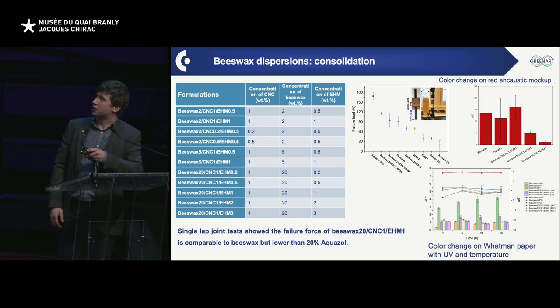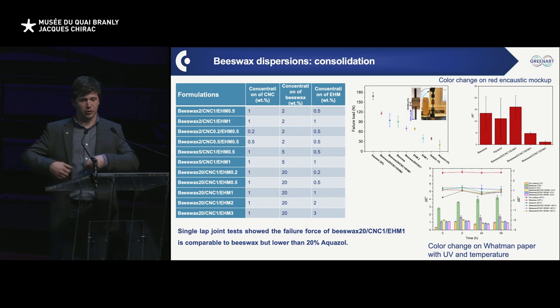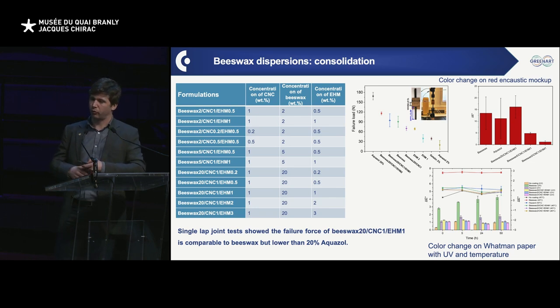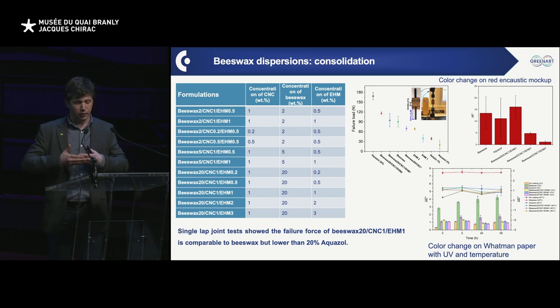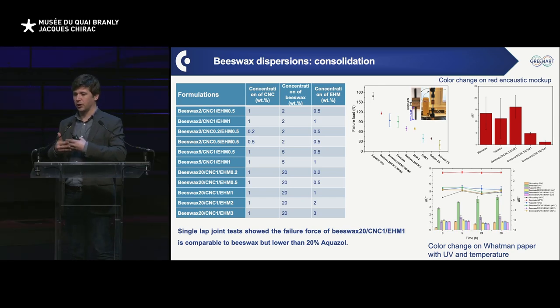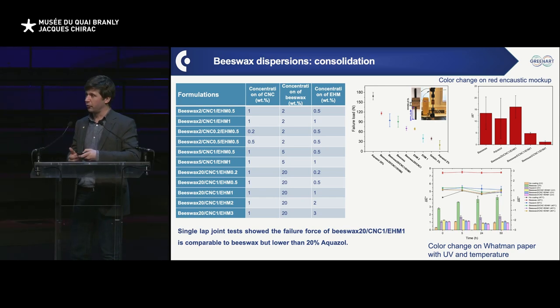And essentially this was the Aquazol 20%, so that's a pretty thick liquid to work with, probably higher than the usual concentration it is worked at. Well, that is the one that is the best. But our system comes close to it, and we still have a very strong resistance, and we have a very good efficacy of the system in working as a glue. On top of it, contrary to Aquazol and some other polymers, we are still very hydrophobic.